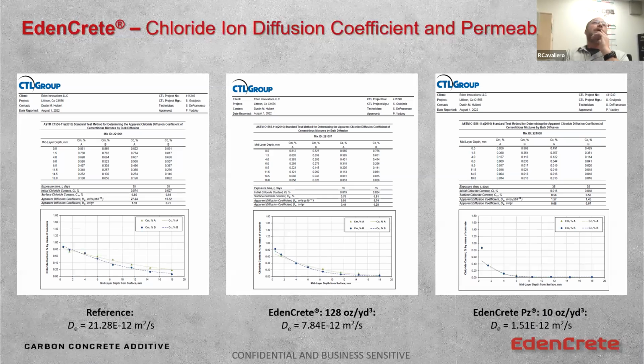When we look at this sample here on the far left, this was a mix that we did just to test our products. This is Colorado DOT's Class BZ Caisson mix. It's a very low permeable 0.31 mix. And it generates basically a graph of the concentration of chloride versus the depth, and then comes up with a coefficient. The reference achieved 21.28.